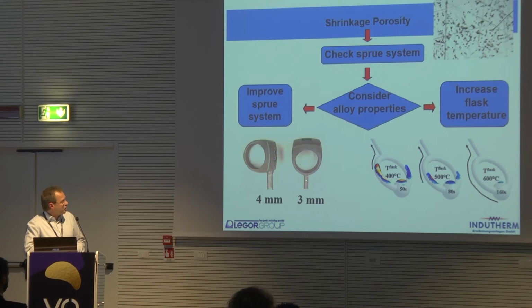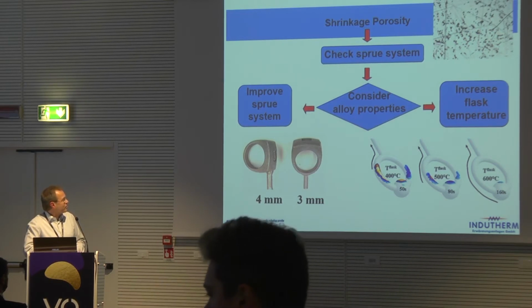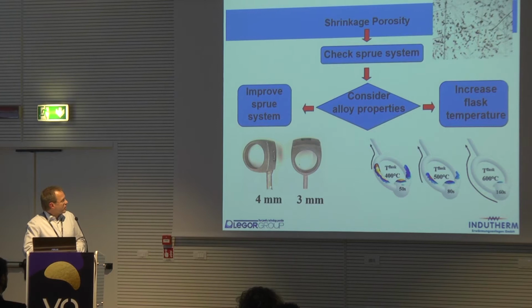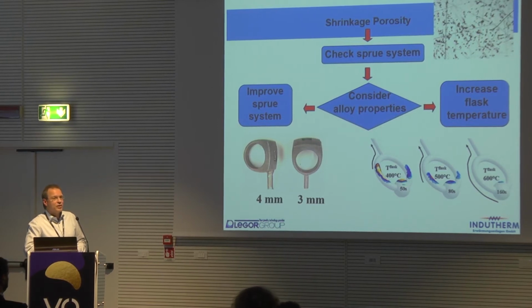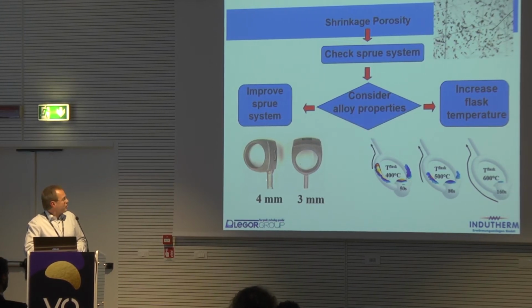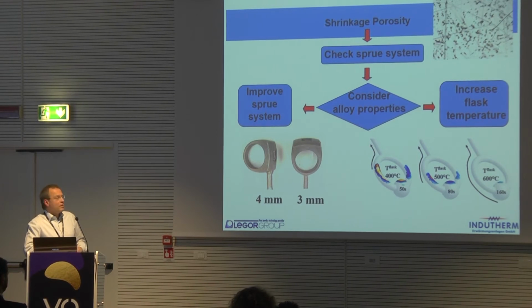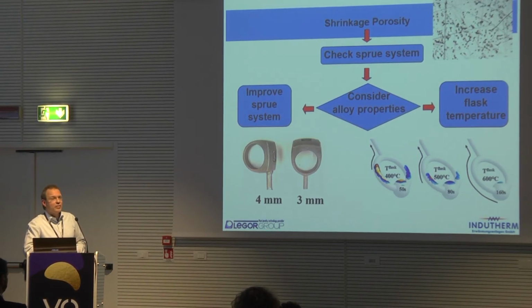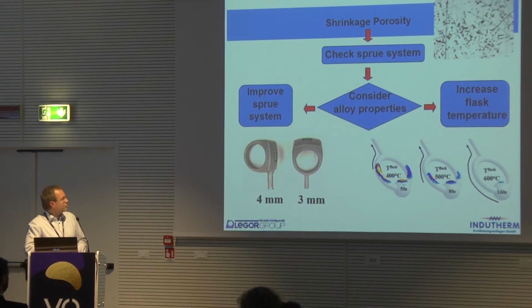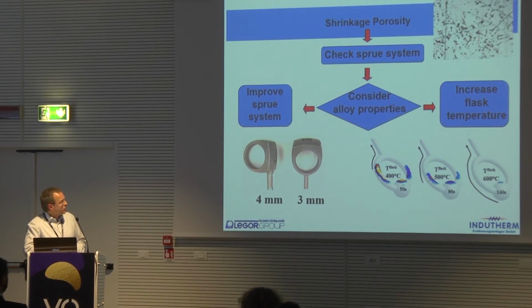So as opposed to putting a tiny sprue opposite to the heavy part of a casting, put a bigger one nearer to the heavy part. And this, in most cases, will help to minimize the problem. The more susceptible the alloy is to shrinkage porosity, the bigger the sprues become, the shorter they become, and in extreme cases, we will also use multiple sprues to optimize the situation.